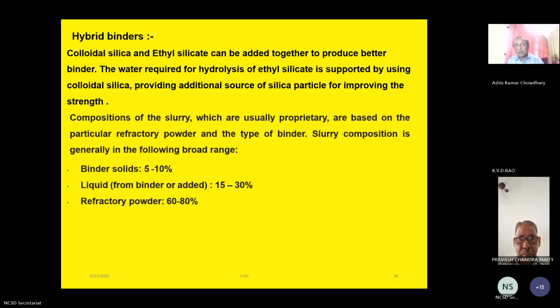Hybrid binder. The colloidal silica and ethyl silicate can be added together to produce better binding. Water required for hydrolysis of ethyl silicate is supplied by using colloidal silica, providing an additional source of silica particles for improving the strength. Compositions of slurry, which are usually proprietary, are based on the particular refractory powder and type of binder. Slurry composition is generally in the following range. Binder solid 5 to 10%, liquid from binder 15 to 30%, and refractory powder 60 to 80%.